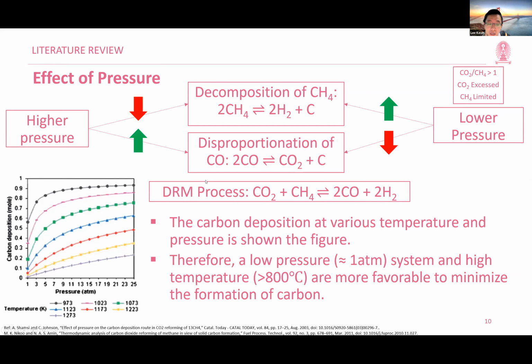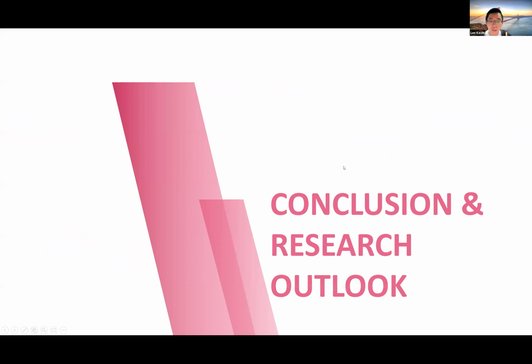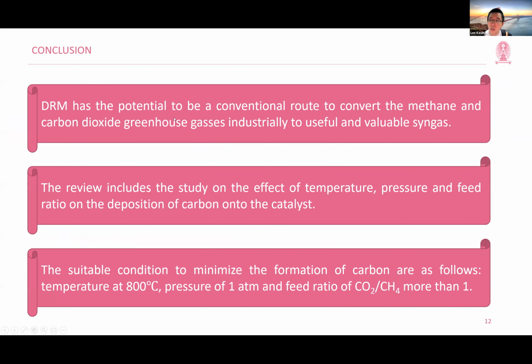If you look at the DRM process, carbon dioxide is a main product, so in the end it will produce excess carbon dioxide. So if the lower pressure were to discourage this equation, it actually produces less coke compared to higher pressure. Thus, lower pressure at around 1 atm and a high temperature, according to this figure, is favorable to minimize the formation of coke. So as a conclusion and the research outlook, the conclusion is